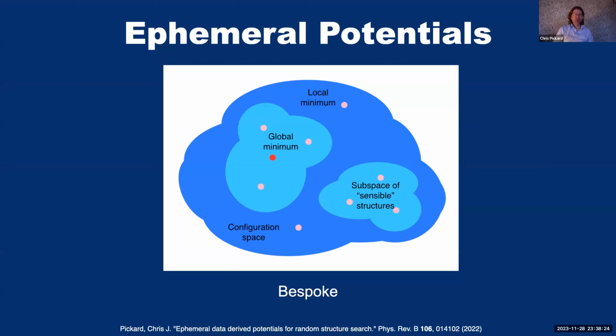I mentioned that before ab initio random structure searching, or first principles structure searching, pretty much the only way that people were doing structure prediction was with empirical potentials. But the problem with those potentials, although they were fast, was that they couldn't handle the entire energy landscapes. However, this new generation of machine learning potentials, which are in many ways very similar to the empirical potentials of the past, are now fitted or trained to a much larger data set. And so there's a hope that they might learn an entire energy landscape, which would allow you then to use it in a brute force algorithm such as random structure search.